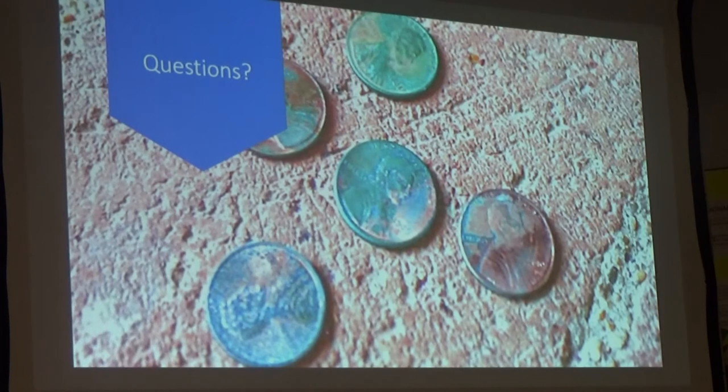Question from the back: You put a silver coin in water in a saucer with some aluminum foil on it and it cleans the tarnish off naturally — what happens there? That's an electrolytic reaction, a contact reaction. Aluminum is more reactive than silver and it will electrolytically clean it. Another way to clean silver coins inexpensively — though a no-no for collectibles — is to make a dilute solution of baking soda and soak the silver coin in it.